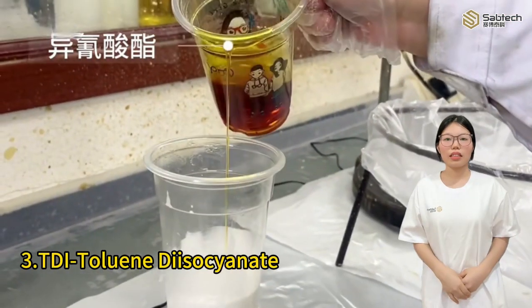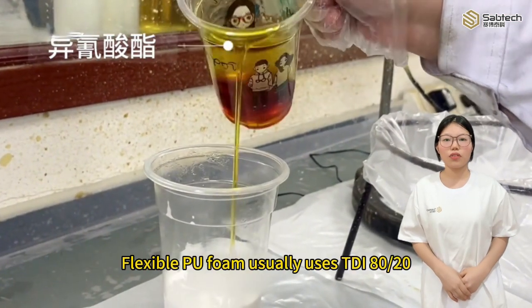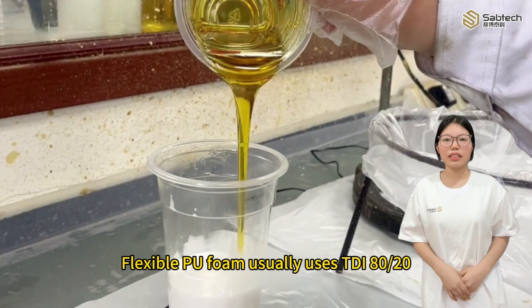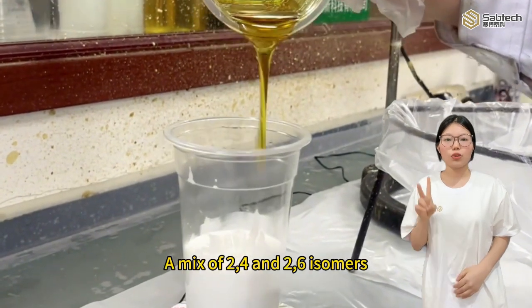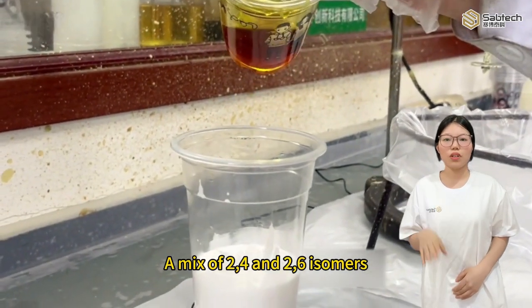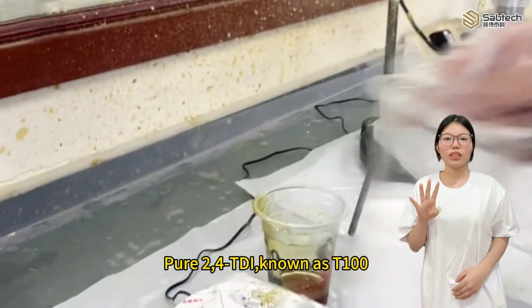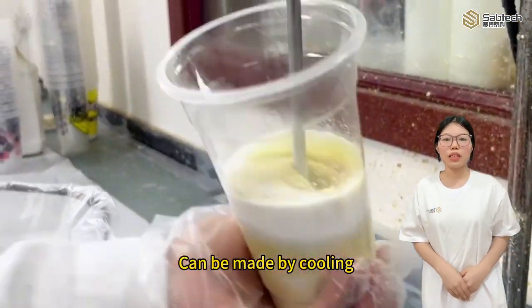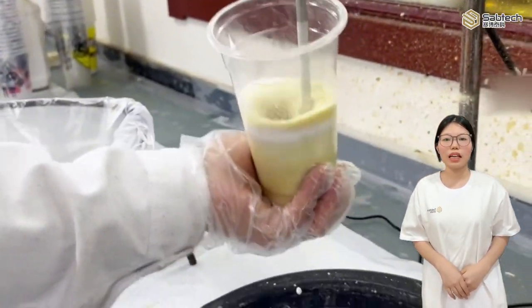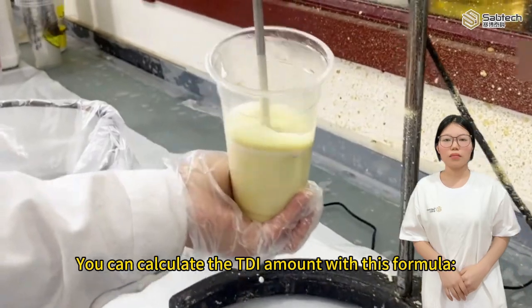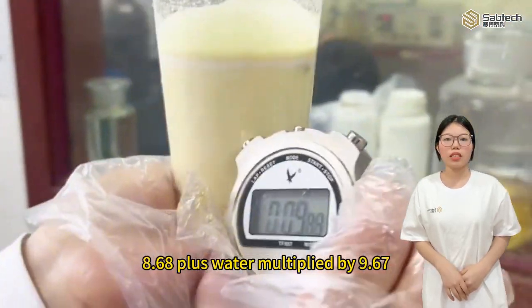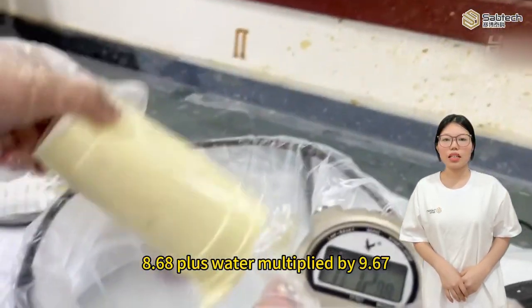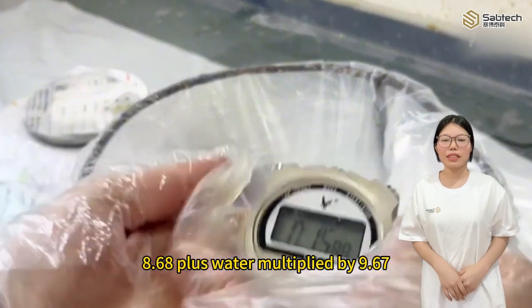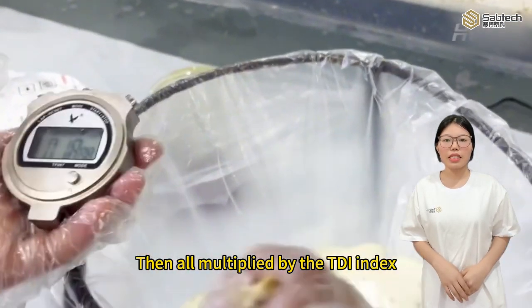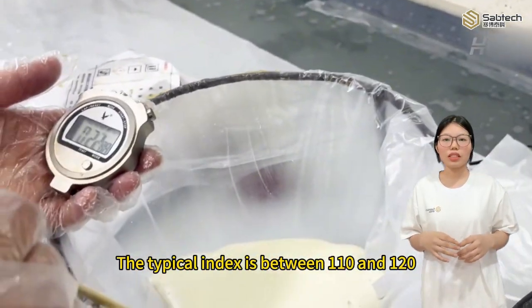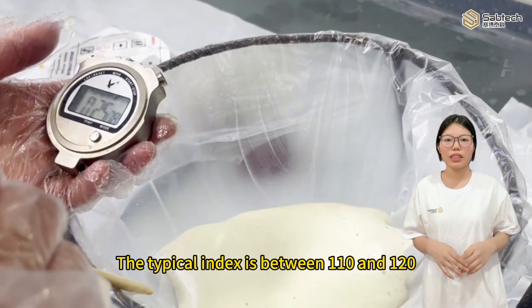Third, TDI, toluene diisocyanate. Flexible foam usually uses TDI 80/20, a mix of 2,4 and 2,6 isomers. Pure 2,4 TDI, known as T100, can be made by cooling. You can calculate the TDI amount with this formula: 8.68 plus water multiplied by 9.67, then all multiplied by the TDI index. The typical index is between 110 and 120.